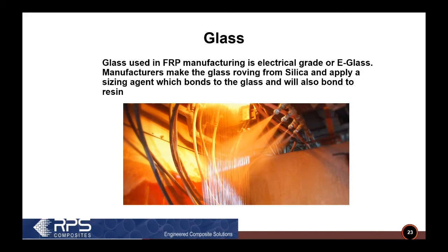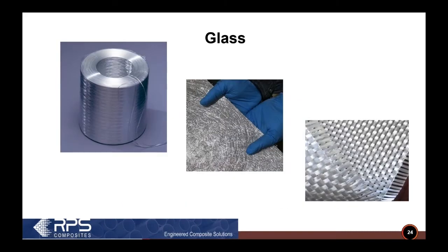Actually, they use something called silane. And what that does is that sizing agent bonds to the glass and the resin bonds to the sizing agent, and that's how you get a bond between the glass and the resin. The glass actually comes out in a glass roving, like you can see on the left-hand side, but you can imagine that glass roving is going to be a little difficult to use to make a 1-inch flange, for example.